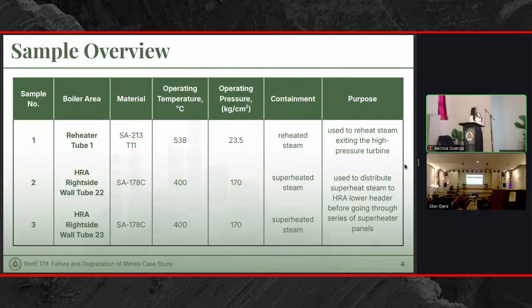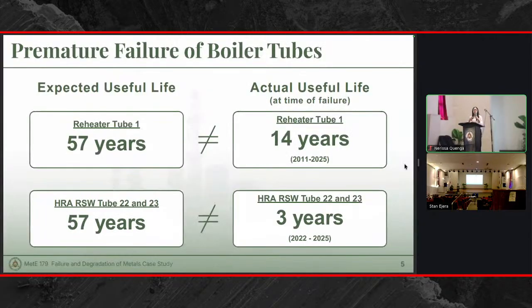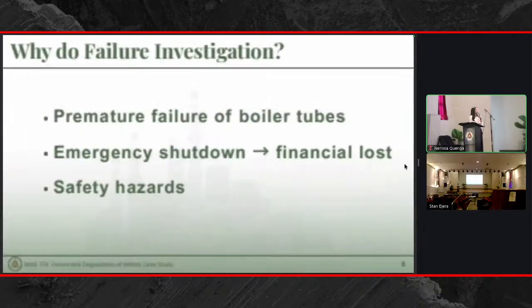So its working condition is presented here. All these tubes are expected to have a useful life of 57 years. However, sample 1 or tube 1 failed after 14 years, and sample 2 and 3 or tube 22 and 23 failed after 3 years. Thus, we are conducting a failure investigation because these tubes experienced premature failure. Moreover, the emergency shutdown caused by the failure of these tubes led to financial losses and safety hazards for the company.